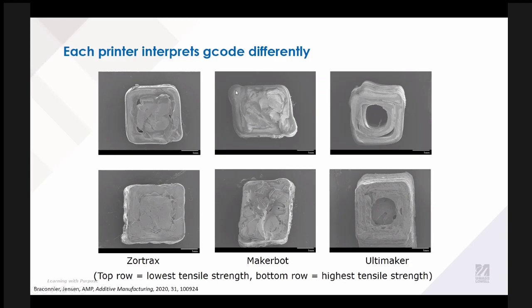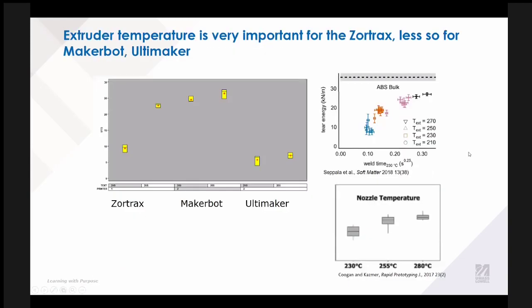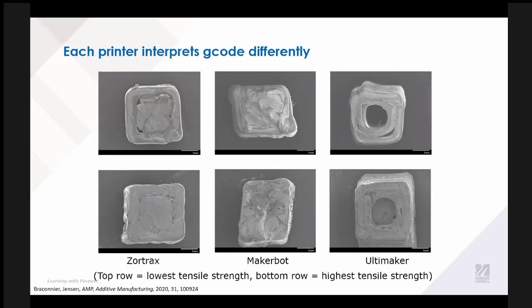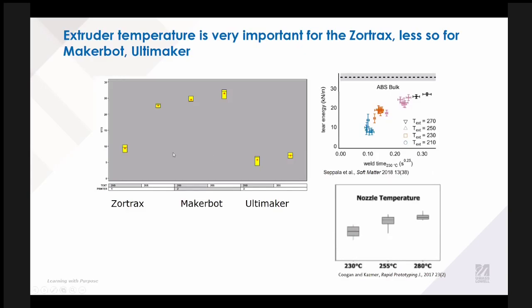Whereas in the MakerBot, there was this more parallelogram that evolves because the G code alternated which side you would start your extrusion from. And then in the Ultimaker, the default was to assume that anything with the dimensions of the dog bone didn't need to be filled, and so even though we said to fill it, the Ultimaker did not fill that hollow center. So here we were seeing a lot of complexity in this very simple type of system. I also wanted to highlight that in the Zortrax, extruder temperature is super important. These are all of the low temperature extruder conditions. These are all the high temperature extruder conditions. Whereas for the MakerBot and the Ultimaker, we don't see that same behavior.